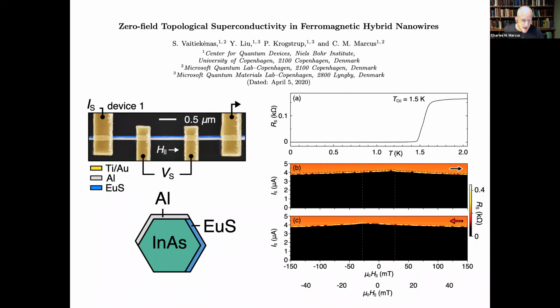I want to contrast this with the behavior of a system in which the europium sulfide is not in direct contact with the aluminum, where it's grown on different facets. And what you see is a couple of things. First of all, the critical temperature is about twice as high. It's a bit steeper, but more importantly, it's about twice as high.